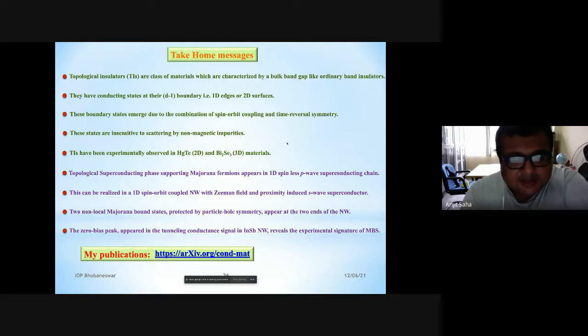And then from the topological superconducting point of view, the more exotic part is that you can have the Majorana fermion that appears in the case of a p-wave superconducting chain, and one can really design or engineer an effective p-wave pairing in a 1D spin orbit coupled nanowire with a Zeeman field and proximity induced superconductivity. And these two non-local Majorana bound states, so it appears as a bound state in condensed matter, are protected by particle-hole symmetry, and they appear at the two ends of the nanowire. So effectively, they form a very non-local state, which is protected by particle-hole symmetry and by the bulk superconducting gap.